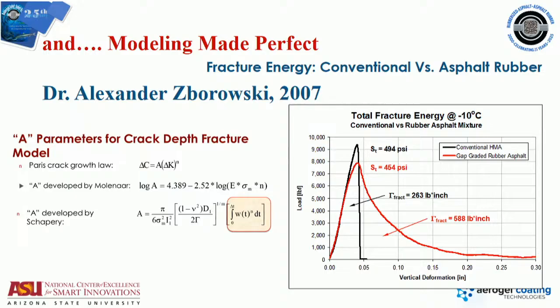But you see the second equation there? That's what is being used right now. That A parameter by Molenaar, what is used in the crack growth law, and I don't want to make this more scientific, a lot of equations here. That A parameter is a function of what? Of E modulus, the stress, and then another constant n in there. It has no fracture energy value whatsoever. They simplified that equation for whatever purpose and it has been used over the years, whereas the original equation by Schapery has a fracture energy parameter. So in simple terms, what Alex did, he just took that second equation, and now all of a sudden, all the predictions that we have in this pavement ME were really right. So again, the message here is, let's make sure that we have confined testing, we understand what parameters we're using, to document it and to relate that to the field.